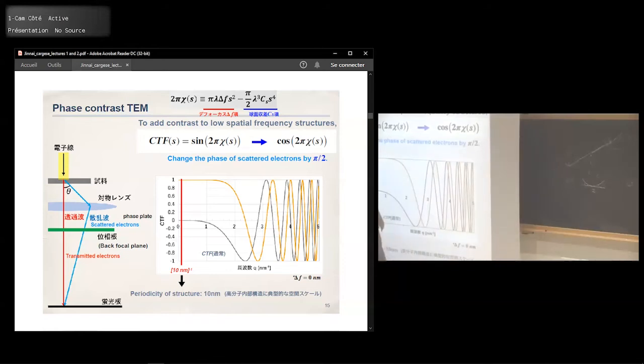So what do we do? We insert a carbon membrane at the back focal plane here. That changes the phase by 90 degrees. It changes the function from sine to cosine. Then the CTF becomes like this, and then we have a contrast. Actually, this cartoon is not quite right. We should have a little hole, so that the transmitted electron doesn't experience the phase change, whereas the scattered electrons here experience a dramatic phase change. Then we can have this situation.